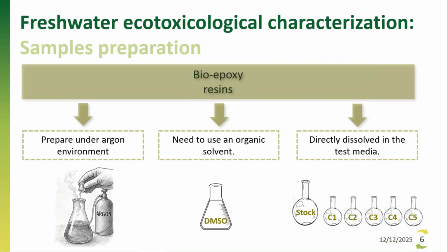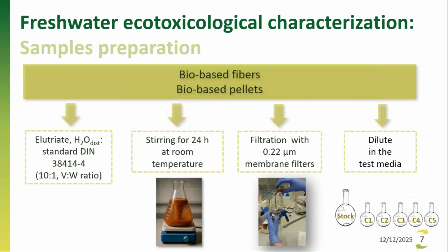Also, when preparing, for instance, stock solutions for these resins, most of them are insoluble in water. So the first step is to dissolve them in a polar solvent such as DMSO at the lowest concentration necessary just to fully dissolve the resin, and then prepare the subsequent concentrations using this stock solution with the appropriate media that we use for each specific freshwater species.